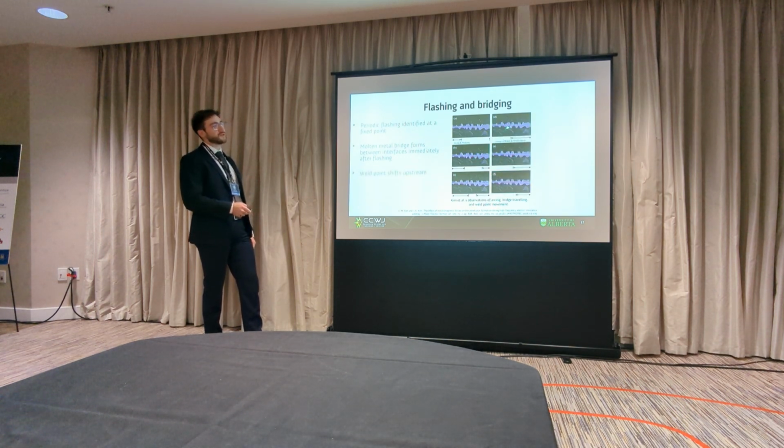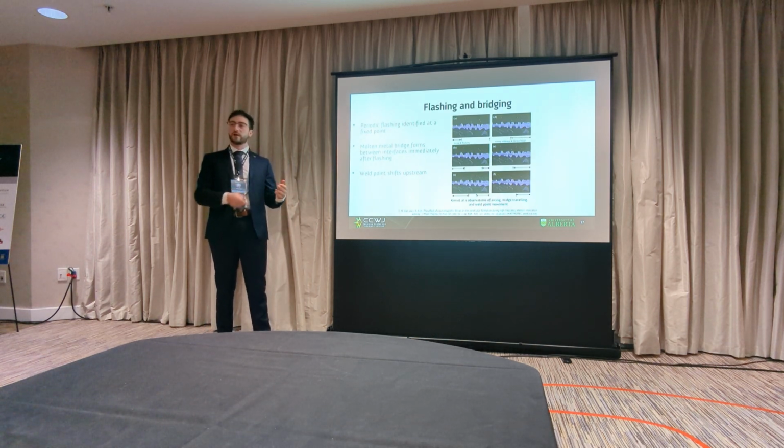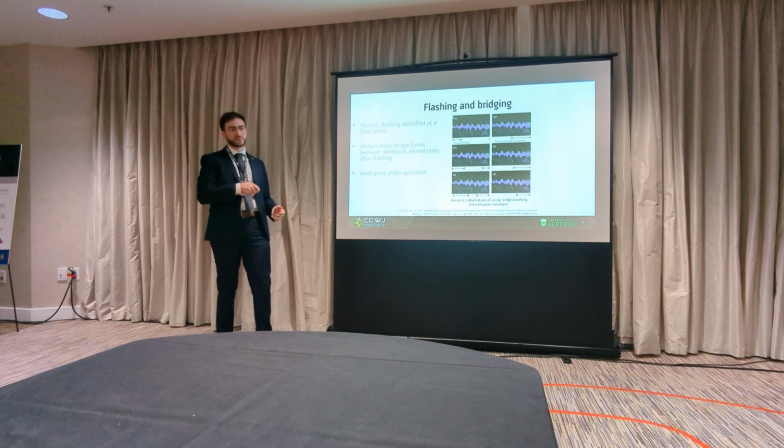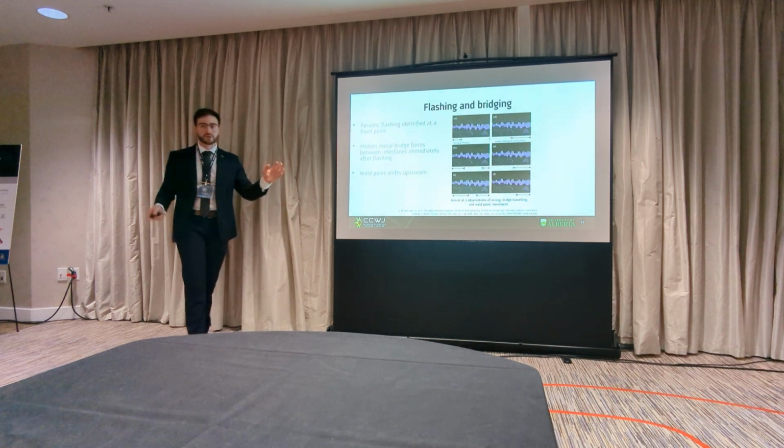After that, eventually the molten metal bridge is moving downstream, hits that weld metal that has been moved up, and now both of them start to move back downstream in unison, eventually until the original conditions of the process were achieved. This is the periodic nature of the process at high heat inputs. How does this relate to penetrators?